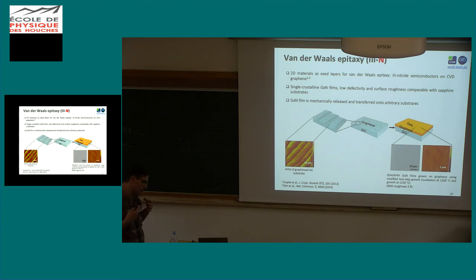Since you only have van der Waals interaction between the substrate and the crystal you are growing, you might have some nucleation here and there, and then all the atoms that are arriving are basically sliding on top of the graphene, looking for the first nucleus, and then they start to grow these crystals, and you can get very, very large crystals. Otherwise, if you do that on a simple silicon carbide substrate, you will have nucleation everywhere, and you will have very, very small grains.